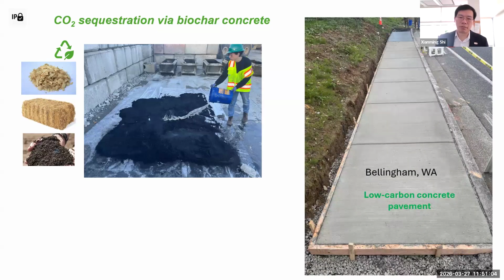And then we deployed about 145 feet of sidewalks with various mix designs, the 5%, 10%, whatnot. Each mix side by side with some control mix designs, we embedded sensors to measure strain, temperature, and moisture every 20 seconds. So we've got more than 18 months of data so far. We need to analyze the data and potentially publish it next year. The main observation so far was, yes, we're seeing a little bit more cumulative strain in the biochar amended concrete, even though it's not to the concern level. Mostly because, again, of the moisture, the water absorptivity we were talking about earlier. So in other words, if we are concerned about that, we should incorporate some waterproofing admixture.